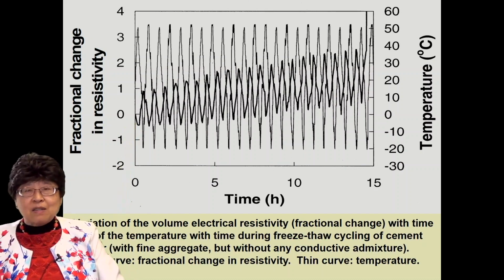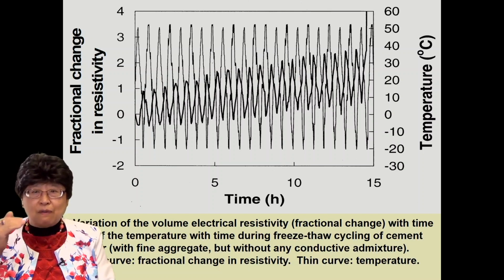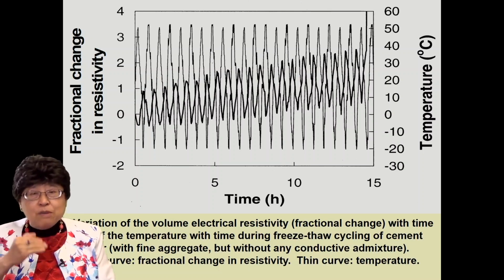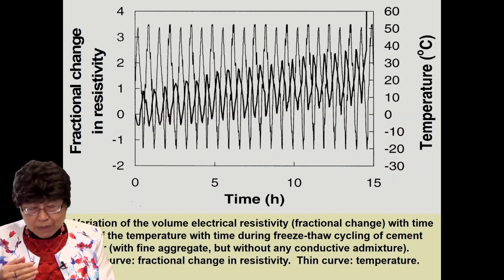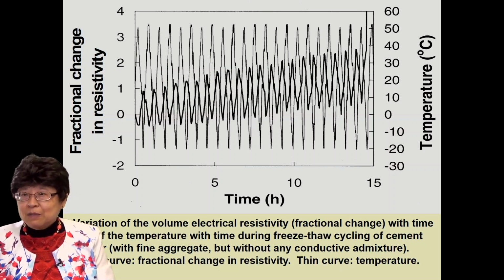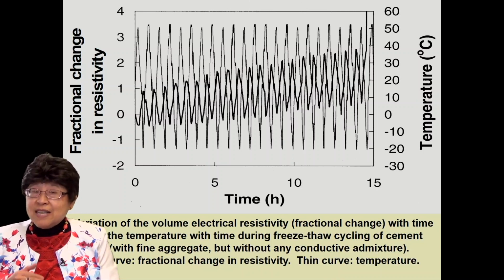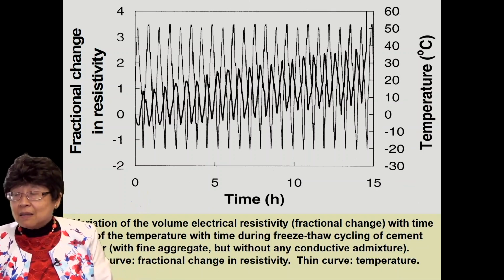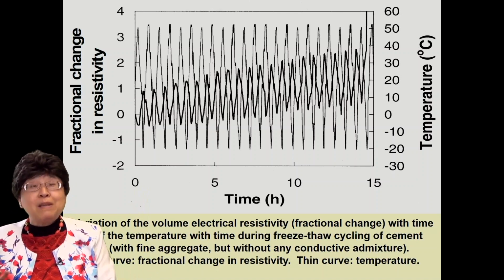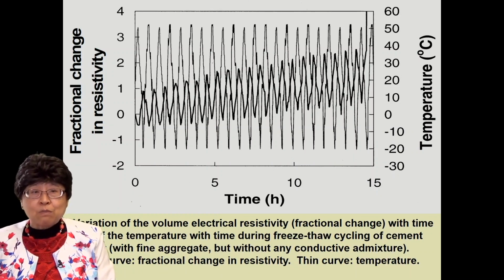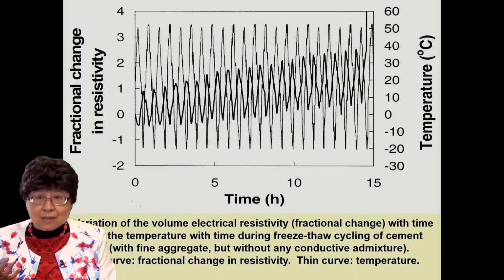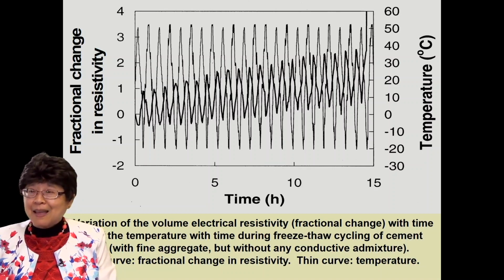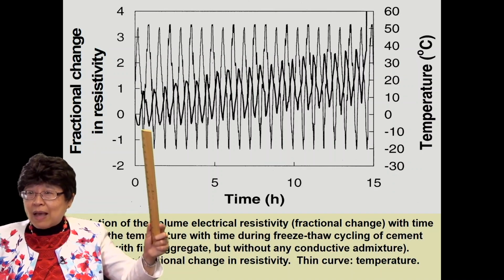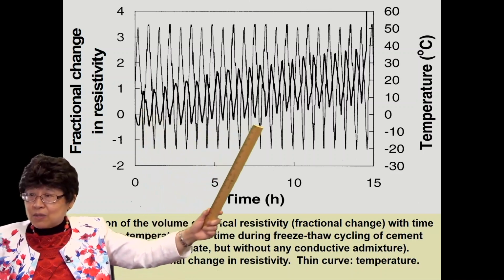Okay? And that is because there is some activation energy involved, some energy barrier involved in the electron jumping across certain interfaces in the material. And so the higher the temperature, the easier the jumping, and so the lower the resistivity. So actually, the cement is a thermistor. A thermistor is a temperature measurement device that functions by the resistivity changing with temperature. So the cement is a thermistor. Okay? And note that as one cycles the temperature,